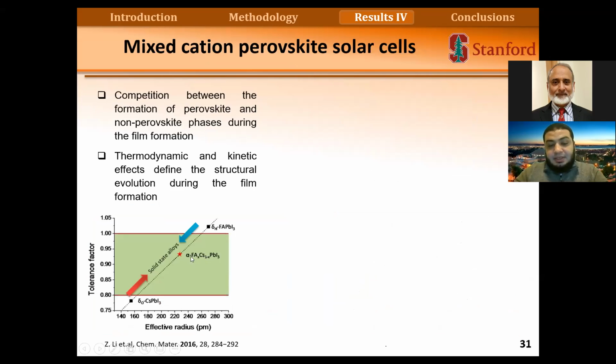I have chosen CsFA. So it's a compound with a cesium atom, and then FA, which is an organic molecule. So this is in the A site with lead and iodide. And this compound has a competition with other phases like a delta phase of FA and a delta phase of cesium, and these can compete with each other during film formation. So we might get stuck with some of these intermediate phases, and we need to form the final product.